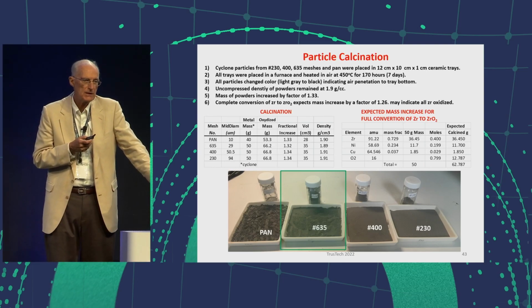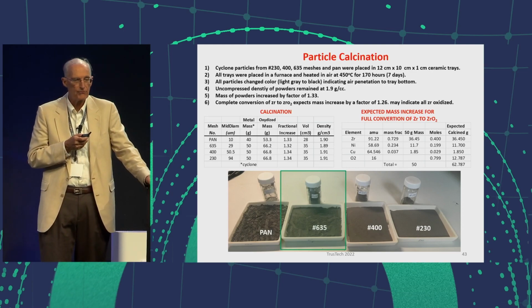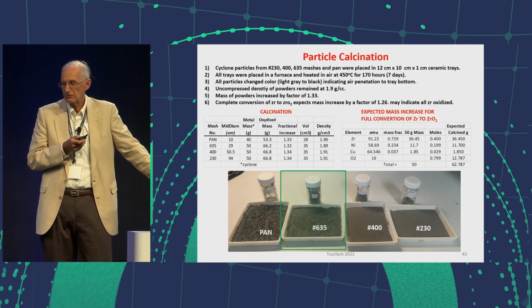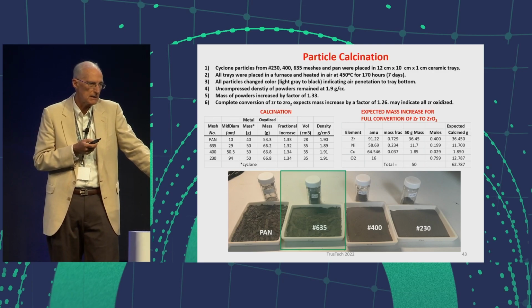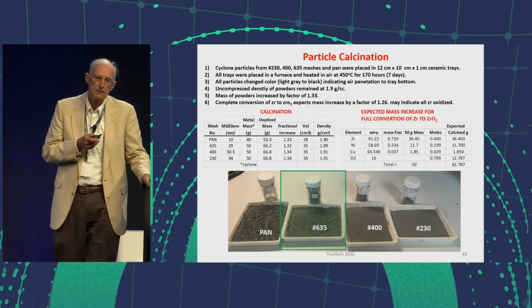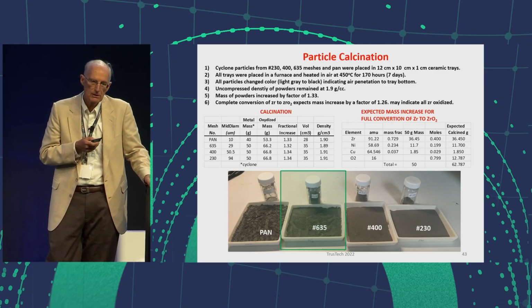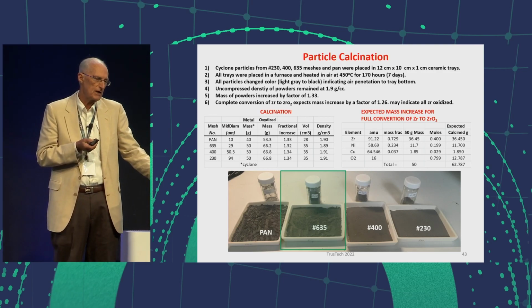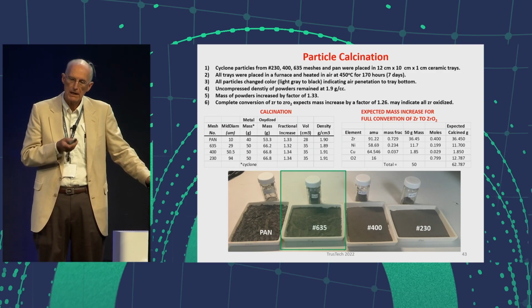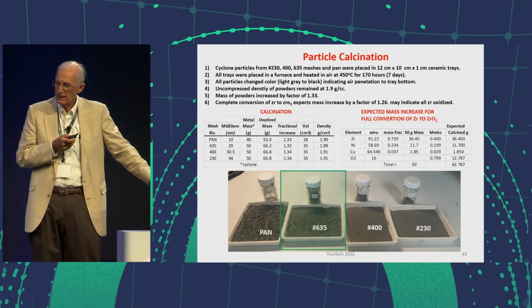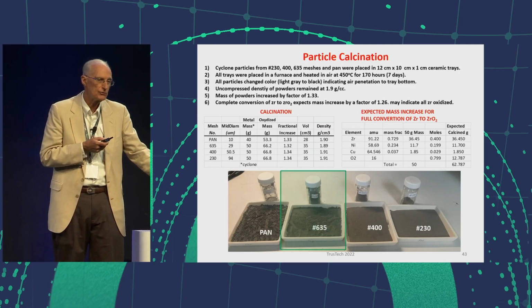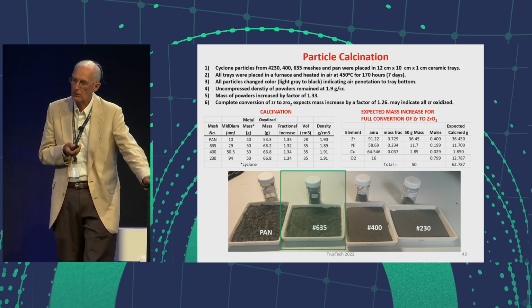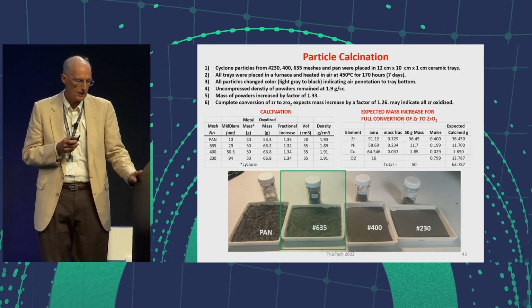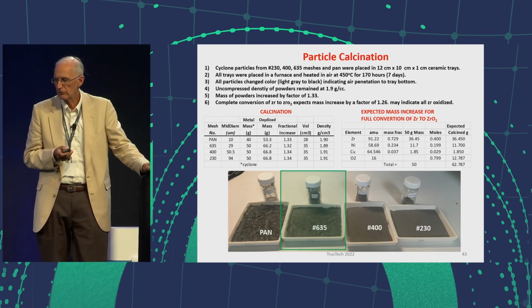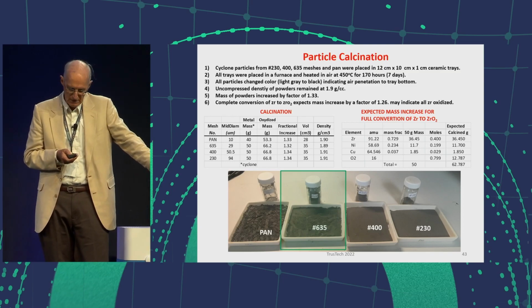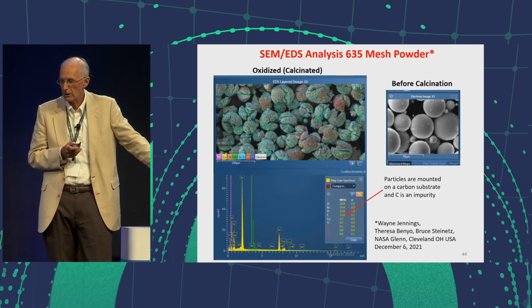And then I measured the increase in mass of the particles before and after and found an increase of mass of 1.33. If you expected all the zirconium in the sample to go to zirconium dioxide, you would expect a mass increase of 1.26, which I exceeded. They actually surprised me that it worked so well, and I thought we might have a chance of making this material work.